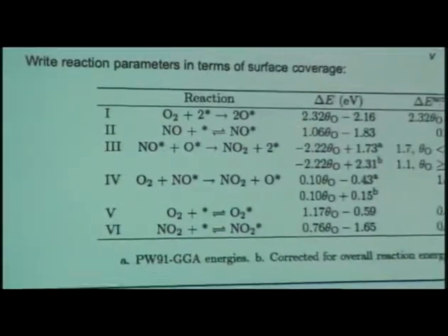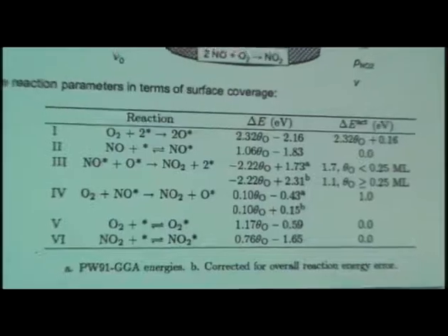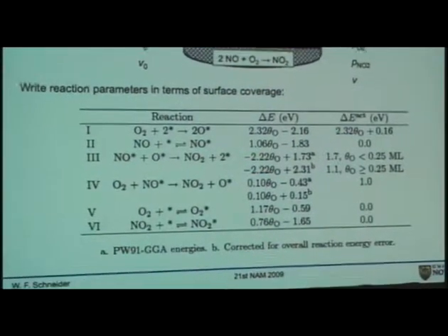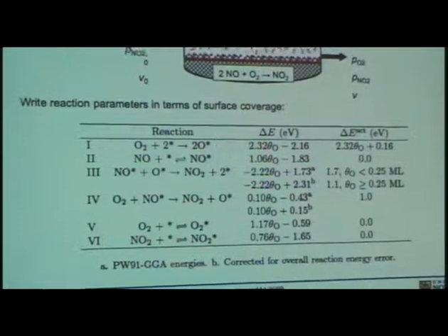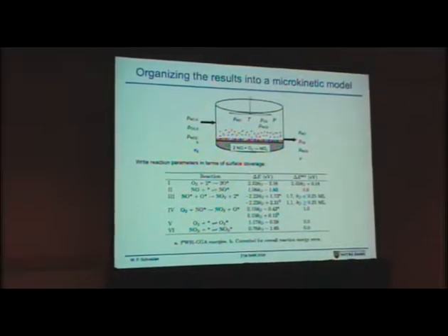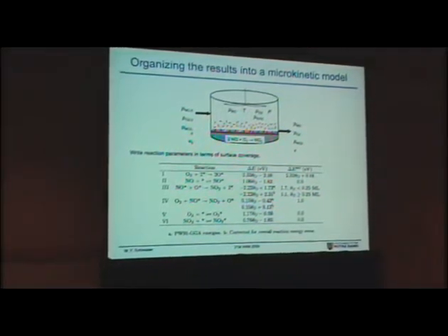We can parameterize, as I just showed you, the energetics of every reaction against the coverage of oxygen. In models, we correlate the activation energies against coverage, and then solve the model to determine whatever we want about the balances. There was one point I'm going to make in here, and that is that you'll see for a couple of these reactions, there are two different lines and two different sets of parameters.